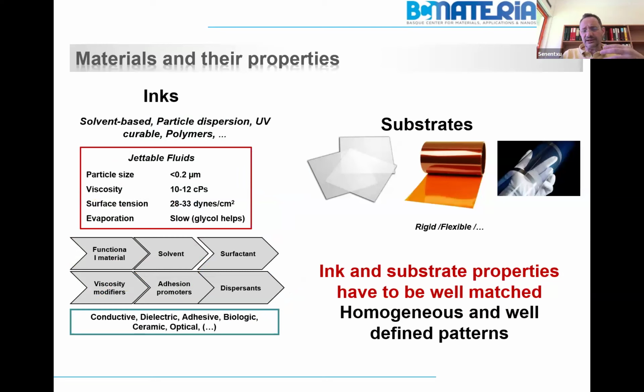And inks, for example, I put here the example of inkjet printing because it's one of the most complex technologies that we have. Inks can be solvent-based, can be dispersions of particles, can be UV curable, can be based on polymer, but we have to have a jettable fluid, with a lot of problems. The particle size has to be below 0.2 microns, the viscosity in this case has to be very low, below 12 centipoise, and surface tension is always an issue. And typically inks become very complex. They have the functional materials dispersed in a solvent, we need a surfactant so that there is no aggregation of particles, viscosity modifiers so that we have a viscosity that is compatible with the processing technologies, and eventual adhesion promoters so that it has proper adhesion with the substrate. And this is complex. As all the materials and all the processes nowadays have to be sustainable, the simpler the better, the fewer components the better.